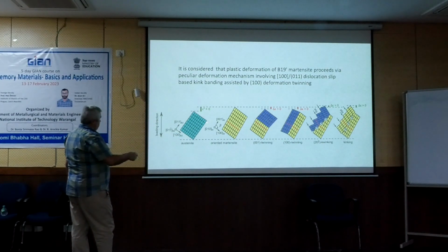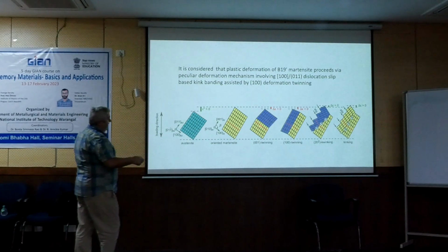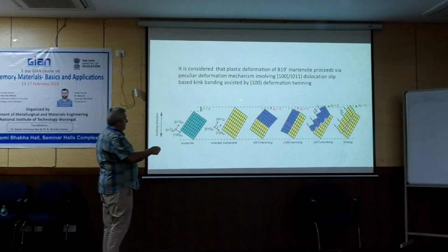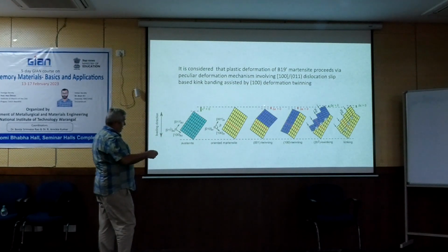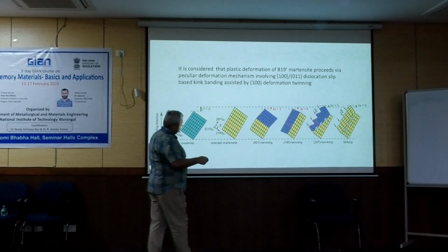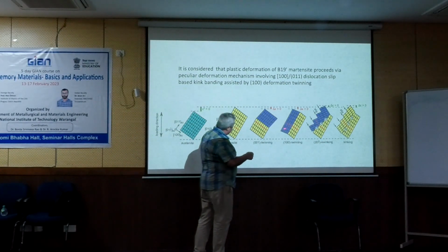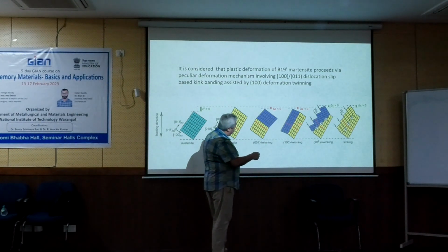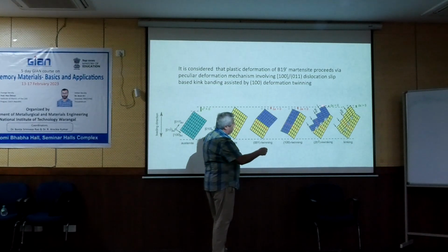So this is the austenite. This is the single variant which is created by stress. So it is longer in this direction, okay? And this is the variant which produces maximum strain. So no further twinning can make it longer. Every twinning which you would consider will make it shorter, okay? But I can assume that the crystal, this yellow crystal, will undergo this twinning, and this twin will immediately deform plastically. So when these two things occur together, I get elongation.